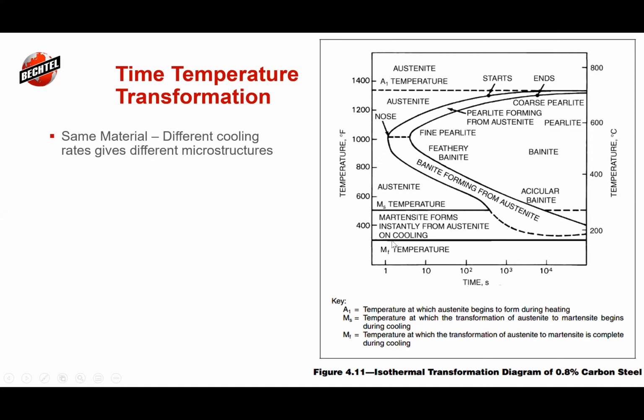And that's why it's so important that on most of our projects, we grind out those arc strikes and make sure that none of that has surface damage, because that martensite will cool down so fast and give a stress riser or a susceptible microstructure.